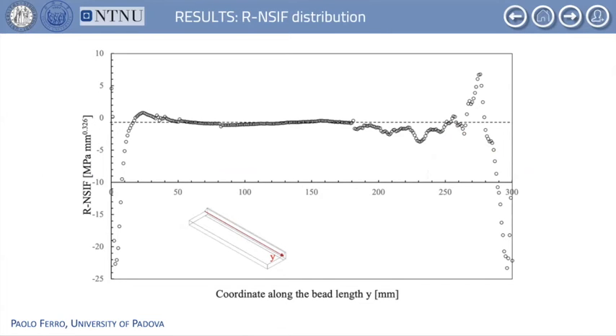This figure shows the residual notch stress intensity factor distribution along the entire weld toe, induced by welding trial number 1. It is observed that the residual notch stress intensity factor distribution is characterized by high variation near the boundaries and a plateau far from them. Such a stationary value is the same that is captured by 2D models, as demonstrated in a recent work published by the same author of this work. The 3D modeling highlights, therefore, the boundary effects that seem more dangerous in terms of high values of residual notch stress intensity factors compared to the stationary residual notch stress intensity factor distribution.